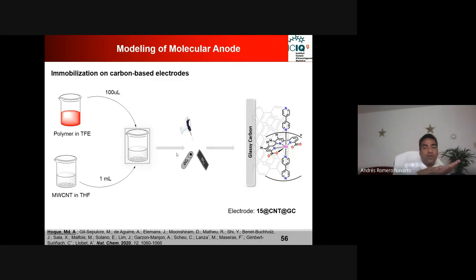And now we found that the system is forming thermodynamically very favorably, so it is going to be more stable. That's perfectly fine, but that was not our main goal, right? We wanted to design the molecular anode. In order to do this water oxidation, we need to put the material we got onto a conductive surface called a glassy carbon disk electrode to do the electrochemistry. So we are putting that one.